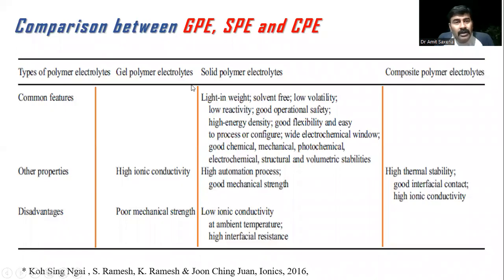When coming to the gel polymer electrolyte, as I mentioned, they offer very high ionic conductivity, but have very poor mechanical strength because of their nature. Solid polymer electrolytes are lightweight, perfectly solvent-free, with low volatility, low reactivity, good operational safety, and they offer moderate ionic conductivity. By some other means, we can increase the ionic conductivity as well. The only problem with this, as mentioned, is low ionic conductivity, but we have different methods where we can increase it. Coming to the composite, it has high thermal stability, good interface contact, and comparatively high ionic conductivity as compared to solid polymer electrolytes.